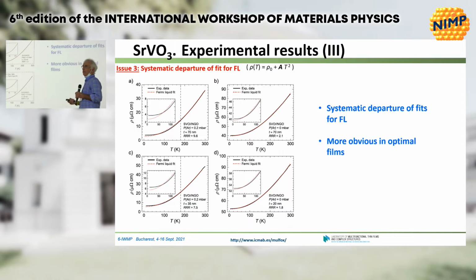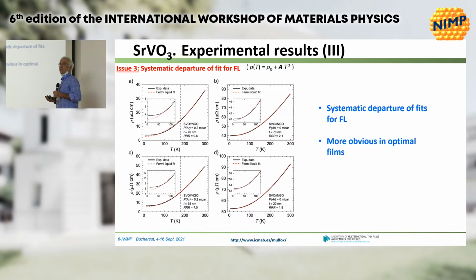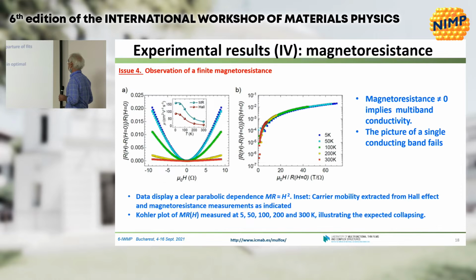So neither the fit, nor the physical dependence of the prefactor of the T-square, nor the value of the amplitude are good enough. So there is a clear problem here, and the discrepancy between the raw experimental data and the fit becomes more obvious as the quality of the film increases. When the residual resistivity is larger, the discrepancy is larger. So this plot or this idea is not convincing.